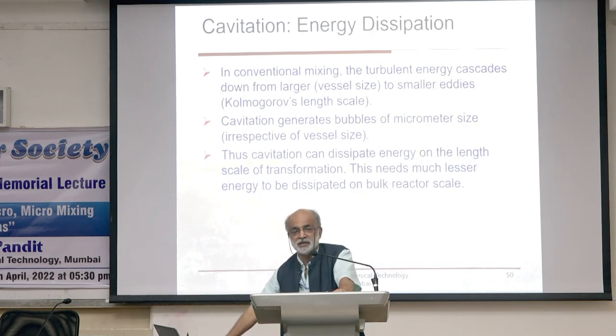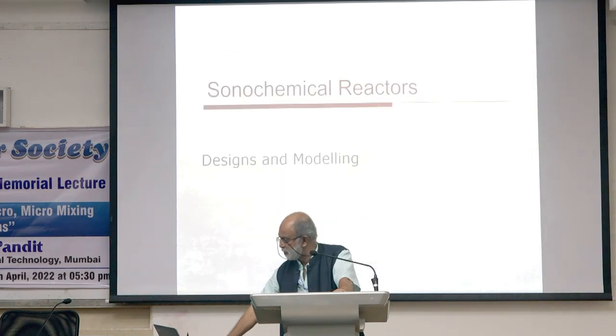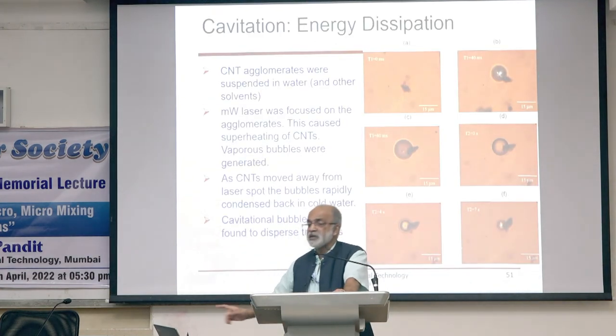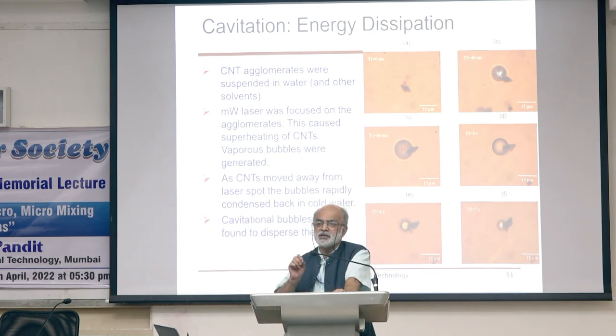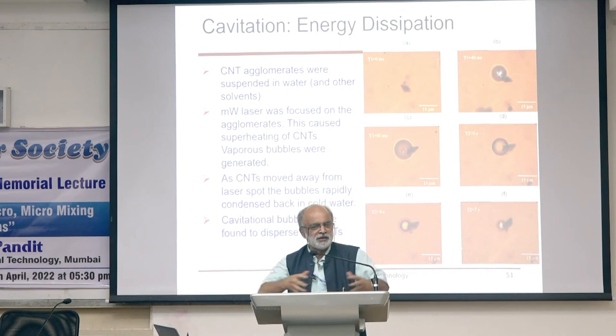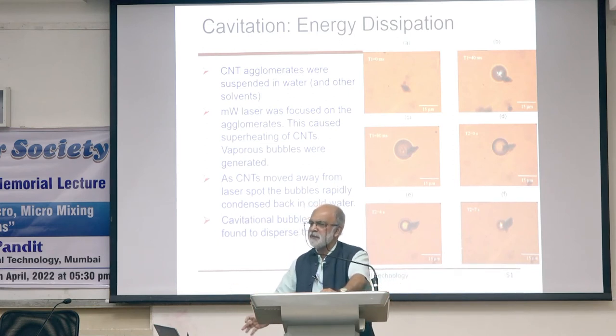in collaboration with TIFR, and we successfully published this work, which clearly showed, on irradiation of a femtosecond laser, how the carbon nanotubes were able to absorb light, increase the temperature, increase the diameter, and the moment the laser stopped, this will collapse, and the collapse of the cavity will result in a dispersion of carbon nanotubes. The same phenomena can be utilized.